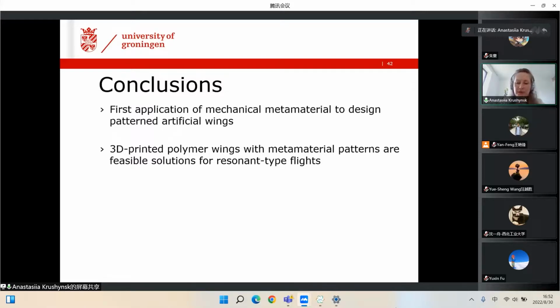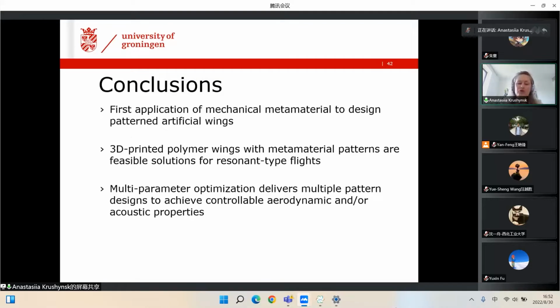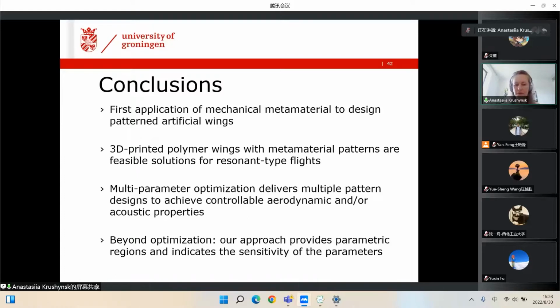Then we developed the multi-parameter optimization scheme that allows us to deliver multiple design patterns to achieve the target properties. And this is actually a step beyond optimization, because this approach gives the regions of the parameter values, indicates the sensitivity of the parameters, and at the end we can have not a single, but a number of designs with suitable flight characteristics. And this is something similar to what we have in nature. In nature, many insects have different patterns, but they are more or less optimized for their flight. So here we achieve a similar result.